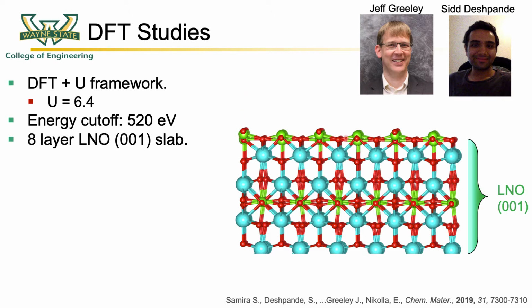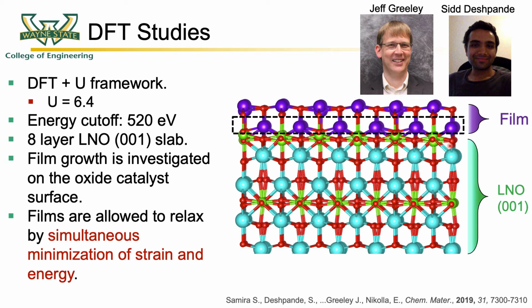The surface termination of these oxides is known to be 001 nickel oxide based on our experimental studies. Hence, that surface structure is used for the modeling of the lithium oxygen species formed during discharge. Both LiO2 and Li2O2-like species were grown on the surface of LNO, and in both cases, a near-surface lithium-rich region was found.